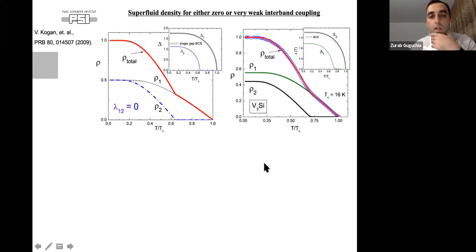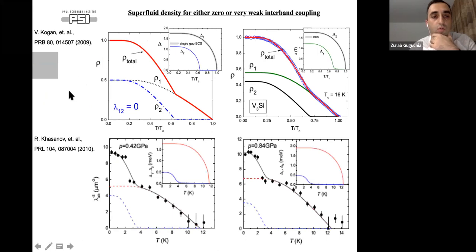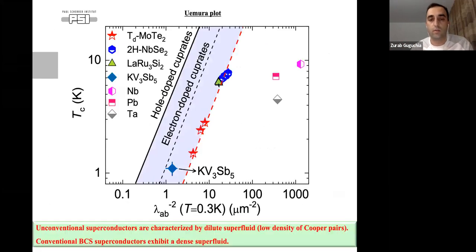So this is reminiscent of the behavior found in these well-known two-band superconductors, iron selenide or vanadium-three silicon, where people see this two-step transition in the superfluid density. This was explained with a very weak interband coupling between the two bands, which gives still the same TC, but this two-step behavior. So we also have a single TC, but two-step superfluid density. Our result is consistent with two-gap superconductivity on two different bands with very weak interband coupling, like in iron selenide or in vanadium-three silicon.